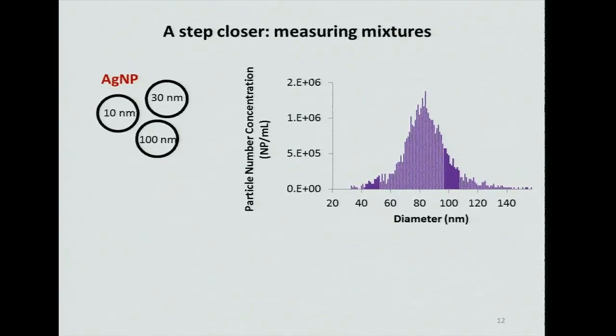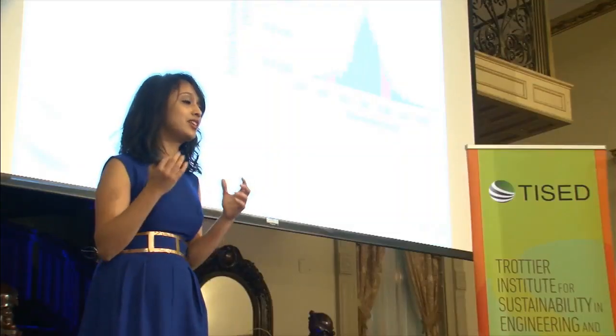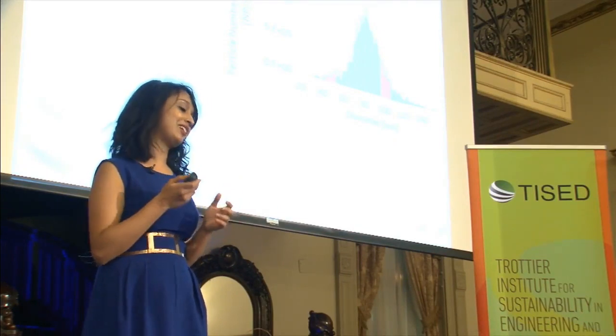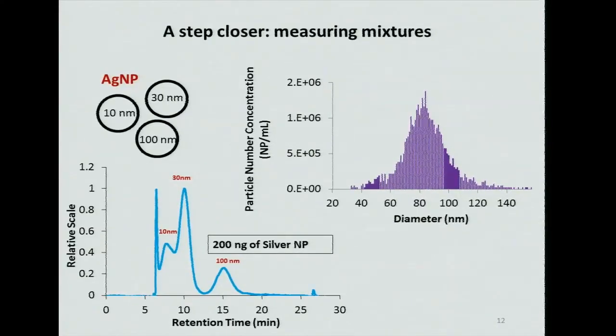And imagine going back to that real sample where you're trying to detect what nanoparticles are present and what compositions they're present in. This method lags behind. So what we next did was use these 3 nanoparticles to separate them using field flow fractionation. And here we have 3 distinct peaks of 10, 30, and 100 nanometers.